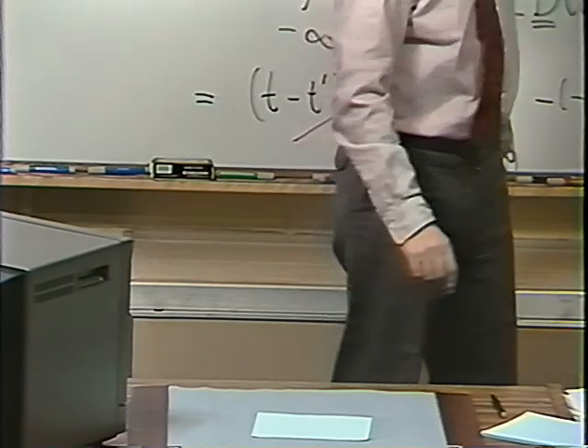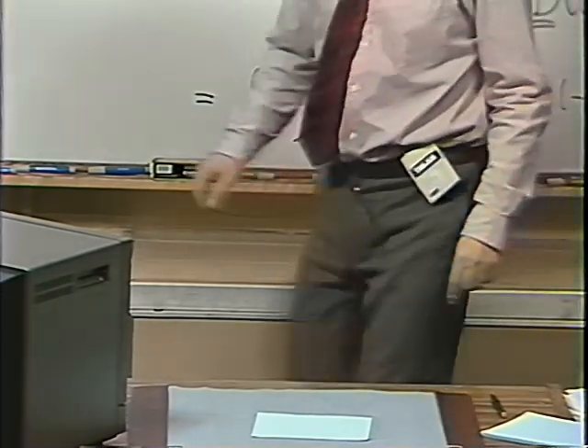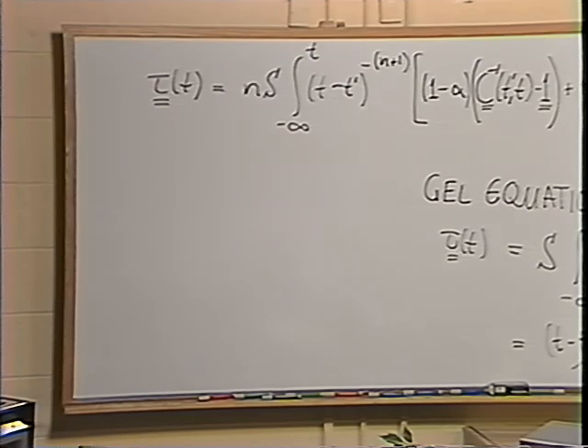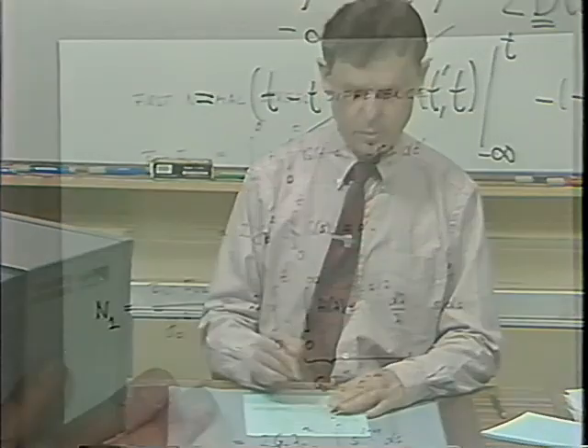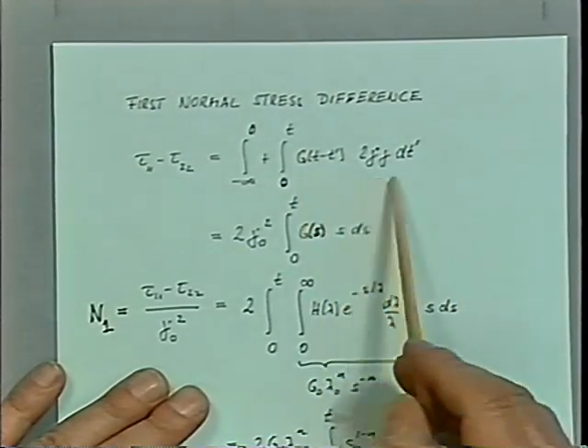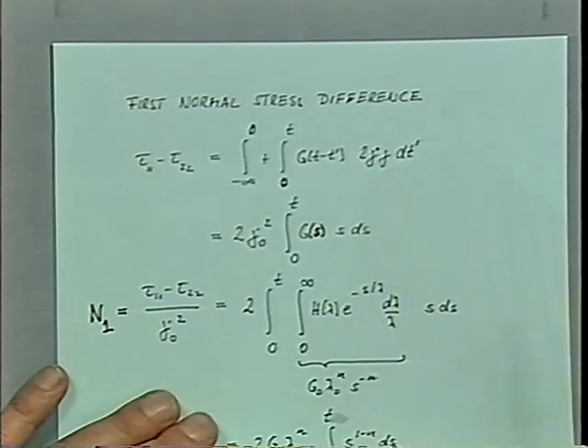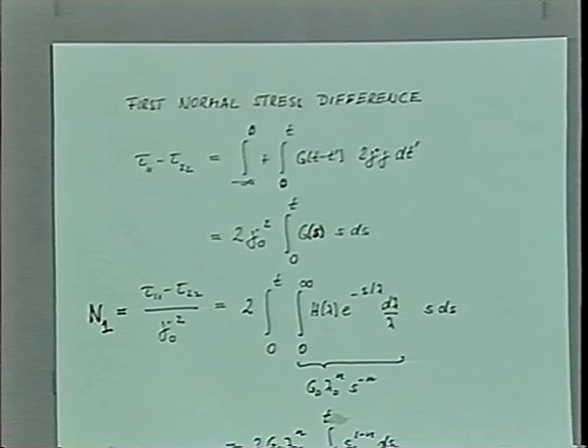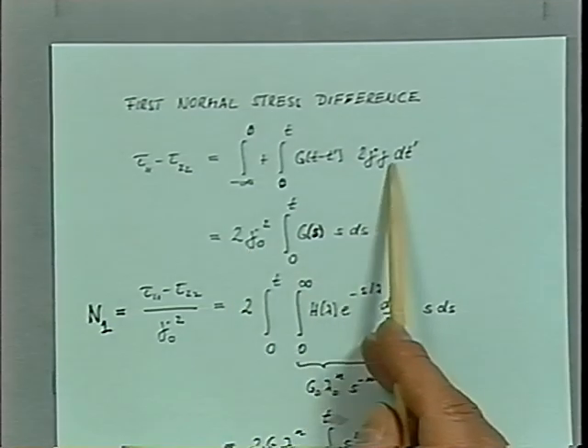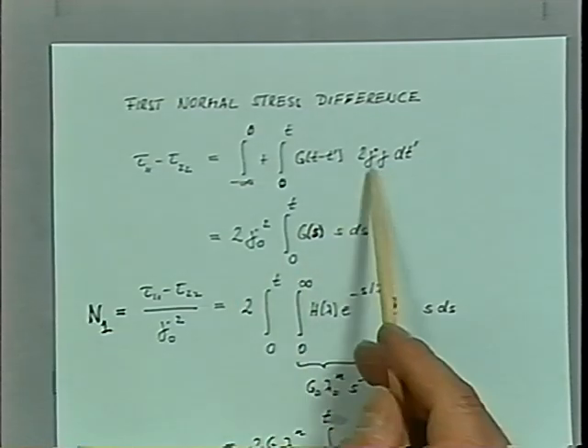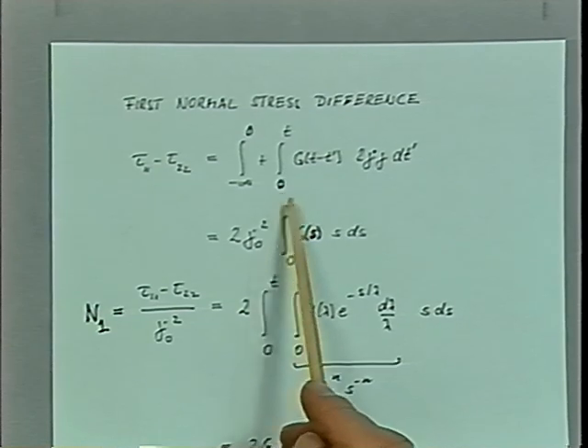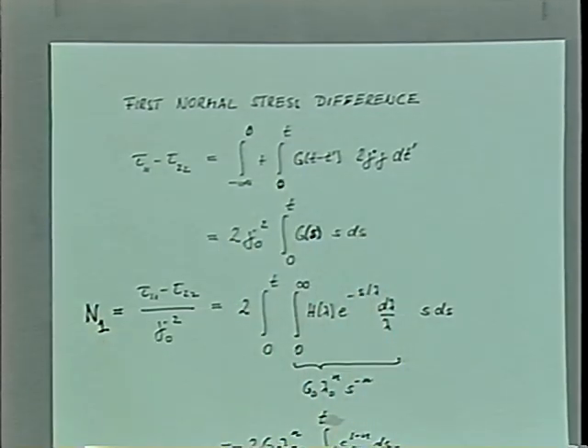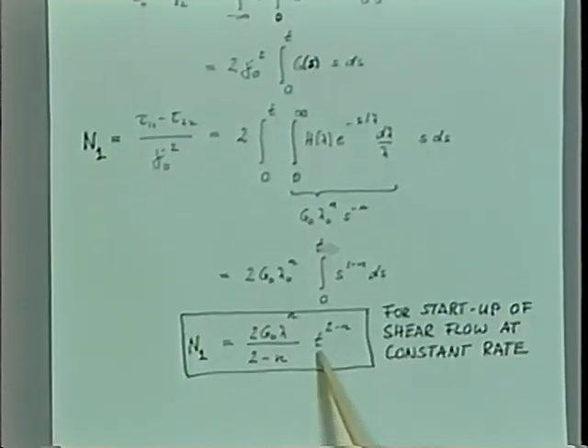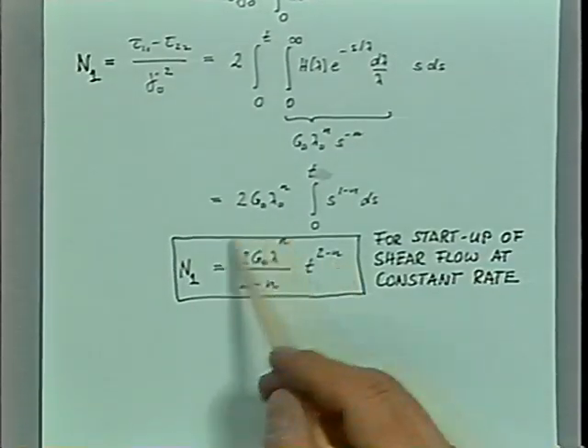So let's take the 1,1 component minus the 2,2 component and calculate the first normal stress difference. So we take the first normal stress difference, tau 1 minus tau 2, which is equal to this integral where we introduce now 2 gamma dot gamma, and we replace that with the time and the rate of deformation. See, gamma is equal to gamma dot 0 times s, and gamma dot is equal to gamma dot 0 in the time range from 0 to t. And then you integrate this and get the first normal stress difference. And you find that the first normal stress difference grows with a parabola with an exponent 2 minus n, and then has a front factor like here.